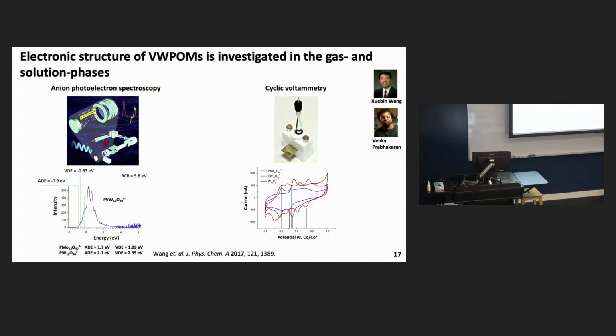Before we proceeded with soft landing, we wanted to understand the electronic structure of this doped cluster in the gas phase, which we did using anion photoelectron spectroscopy. This involves taking one of these mass-selected ions, interrogating it with a laser, and measuring the kinetic energy with which that electron is released. This gives you some insight into the electronic structure, as shown on the left-hand side. As you can see, this 4- species has much lower detachment energy than the comparable species containing molybdenum or tungsten.